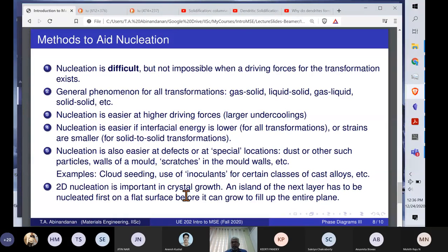Whereas the interface that we are talking about is the circumference of this island, which is a step. And of course, if it is a circular step that you are trying to create, the interfacial term is 2 pi r, as opposed to the volume term, which goes as pi r squared. So you have, again, exactly the same sort of geometric argument.